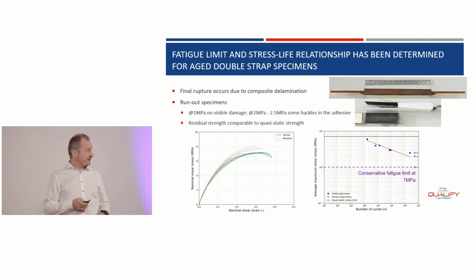All the tests that survived the fatigue were afterwards also tested up to static strength to evaluate if fatigue had any influence on the remaining strength. And that's what you see at the bottom left. The full lines are tests without fatigue. The dashed lines are quasi-static tests on specimens that had been fatigued up to 5 million cycles.